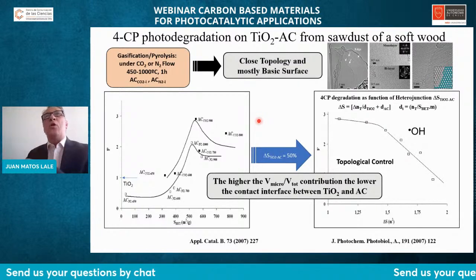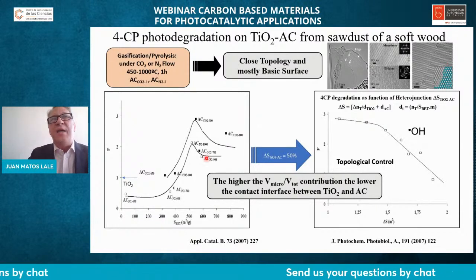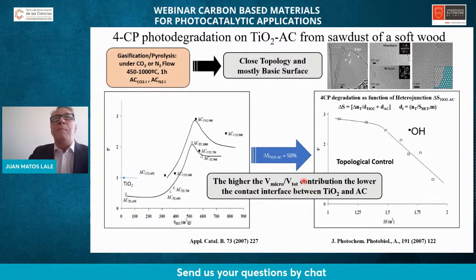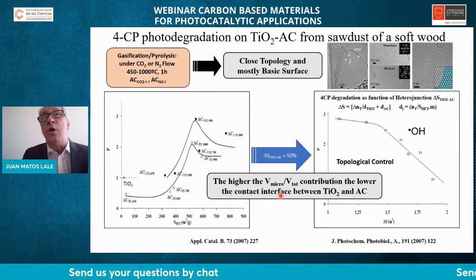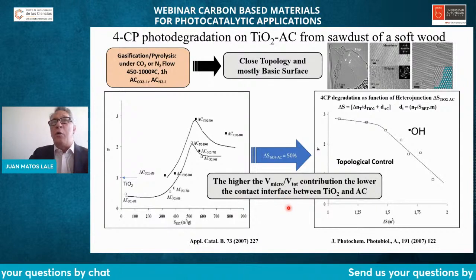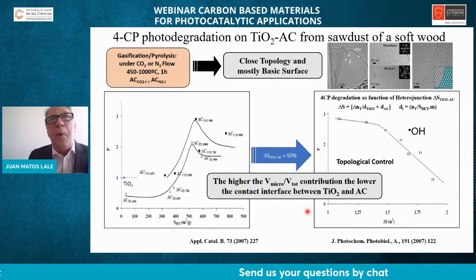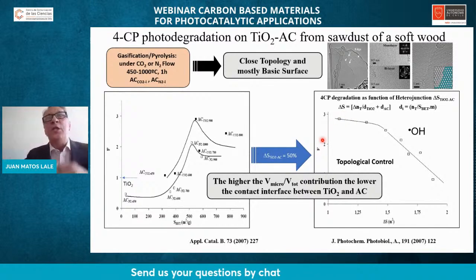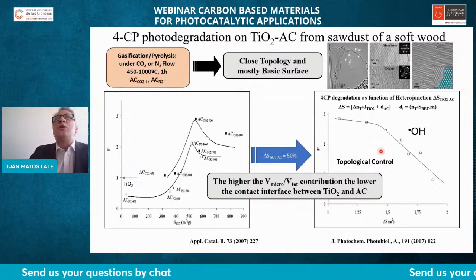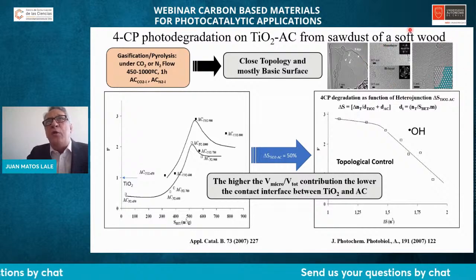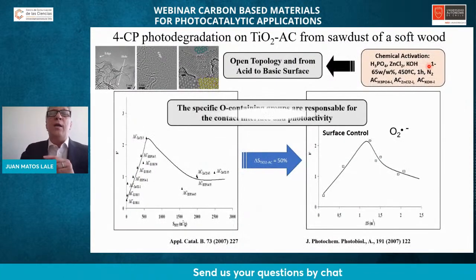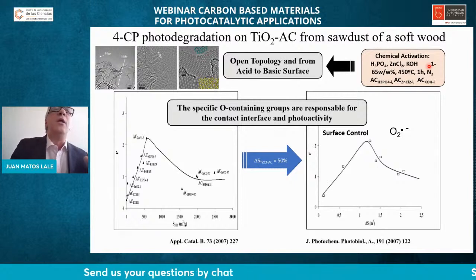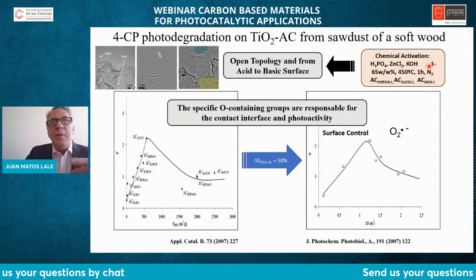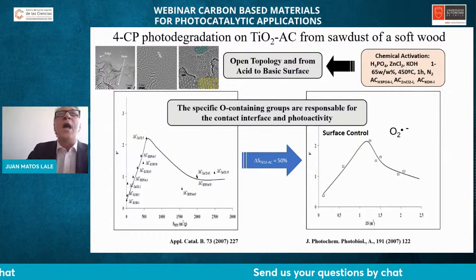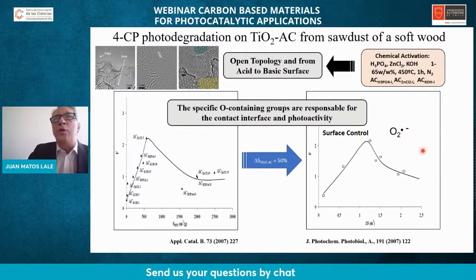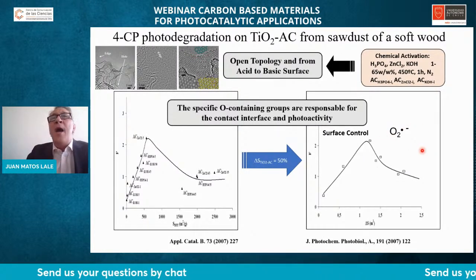Graphene plays the role of semiconductor, more or less in the shape of graphite. And here, the higher the pore confining effect, measured by the ratio between the microporous volume and the total volume of pores, the higher the photoactivity and the synergy between the carbons and titanium dioxide. And it means with the order of the topology. At the same time, if the control is not by the topology but by the surface functionalities, we produce, more importantly, quantities of superoxide anion radicals.